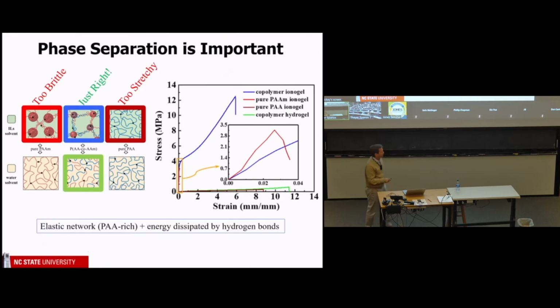So why does this work? Well, this is kind of our best explanation so far. We think that these polymer domains between the phase-separated domains are rubbery. So that gives you the stretchability, the elasticity. But these little domains, it's hard to depict, but if you imagine the polymer collapsing like this on itself, they're hydrogen bonded. And so when you pull them, you're actually having to pull those hydrogen bonds apart, so they break and reform, and that dissipates a lot of energy.